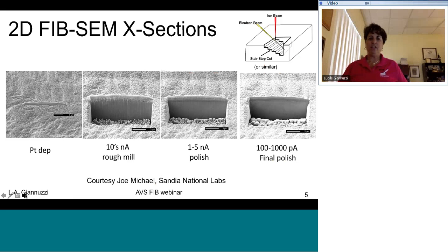So the basic idea for 2D FIB sections is to mark your region of interest with platinum or carbon or tungsten, whatever you have available for you. And this does two things. One, obviously, to mark where you want to cut. It also protects the underlying region from being sputtered away, assuming that's not your sensitive region if you're FIB depositing. The other thing it tends to do is it tends to smooth things out a bit. You can see this particular sample has a little bit of a rough surface, and so this tends to smooth things out with edge and curtain artifacts.